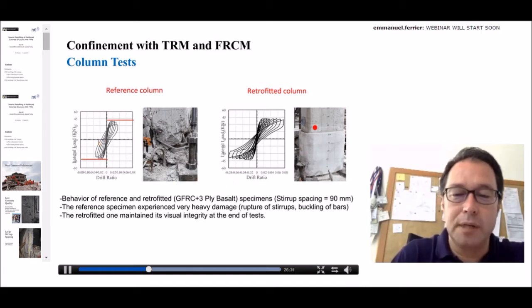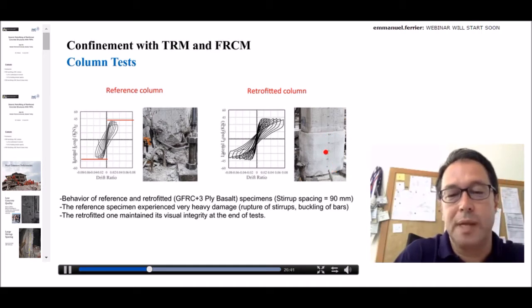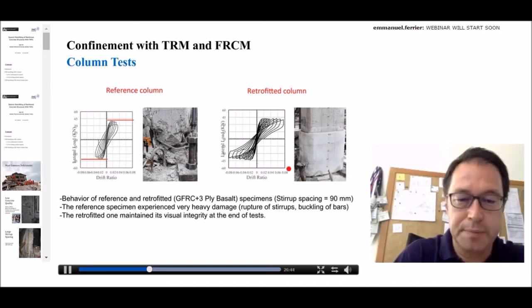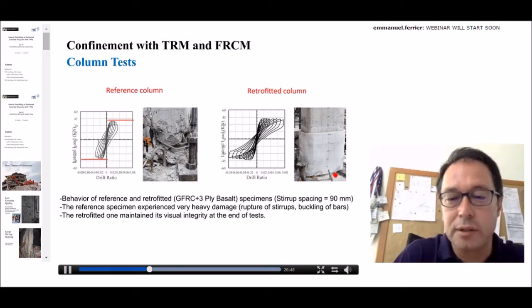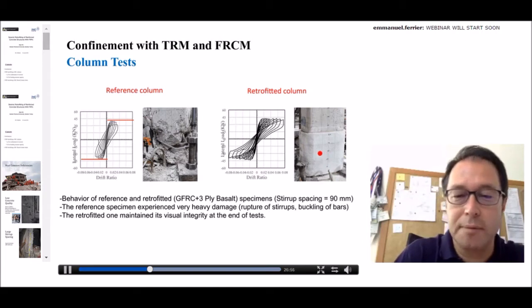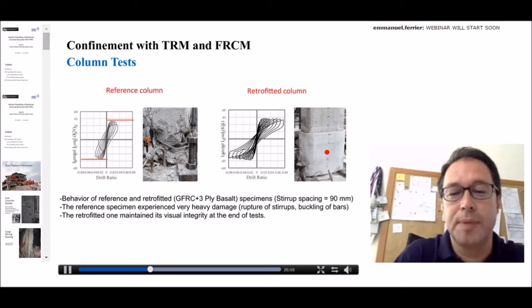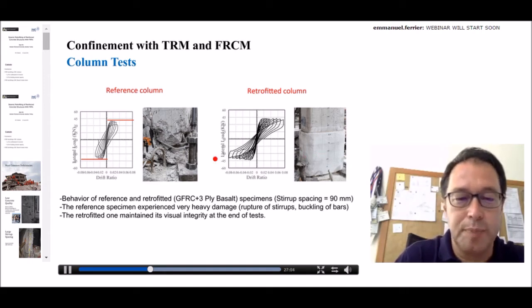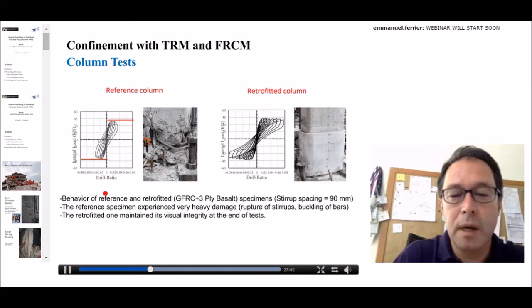On the other hand, if you look at the retrofitted column, here you can see the appearance of this column as well. Just a jacket of 1.5 centimeter thick. And as you see, this was applied on the potential plastic hinge regions, somewhere here, not touching the foundation, to avoid direct axial loading of the jacket. So the jacket was basically subjected to lateral stresses, I could say. And the jacket was only responsible for providing lateral confinement, to improve particular ductility.